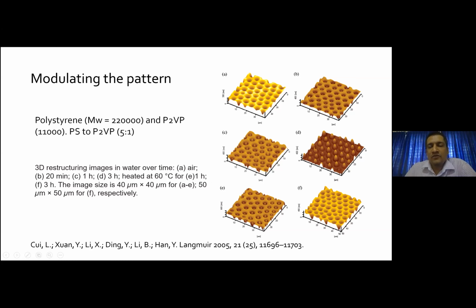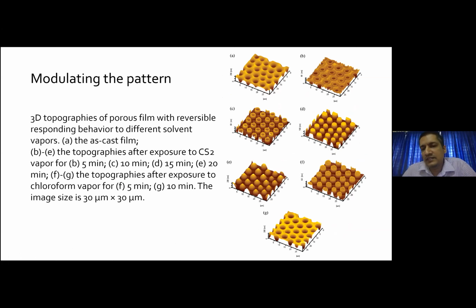Similarly, the same work was done with another solvent, carbon disulfide. Carbon disulfide has different characteristics compared to ethyl alcohol. Carbon disulfide tends to push the polystyrene, and then you get some kind of ring development because of the exposure to carbon disulfide. The same experiment is done by exposing to carbon disulfide, and at each time interval you see how the surface is evolving as a function of the exposure time. And finally, if you get rid of the carbon disulfide by exposing it to chloroform vapors and so on, then what happens is you get back the original pattern which you started with.